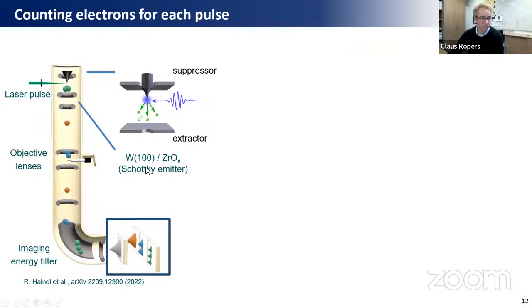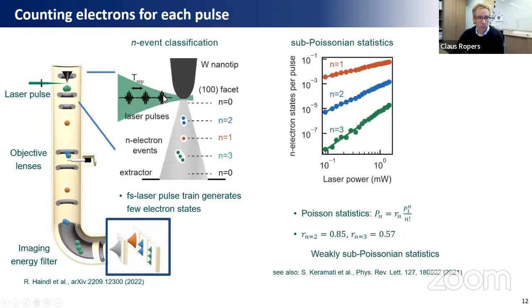So what we can do is basically use a new type of electron detector, which allows us to record the kinetic energy distribution of the electrons emitted within each laser pulse. So basically, we have an electron spectrometer. Say right now, we just take out a sample, we just shoot the laser at the tip, and we record the electron spectrum. Here, we have a sequence of laser pulses. Of course, it's a mode-locked laser, one pulse every nanosecond, but we actually use this at somewhat lower repetition rate, say one pulse every 10 nanoseconds or so.